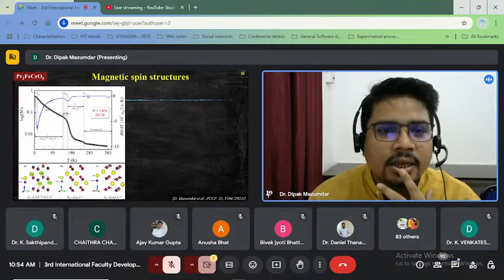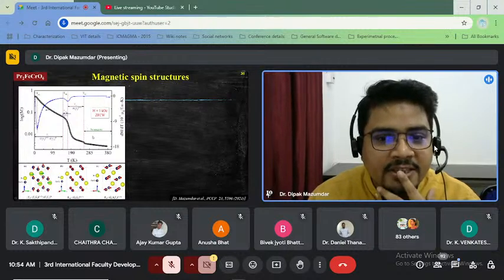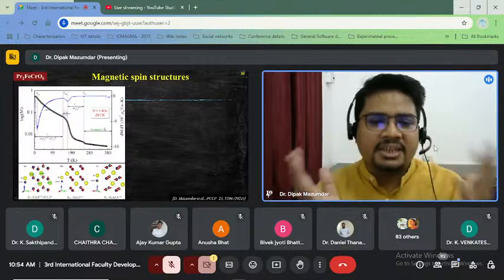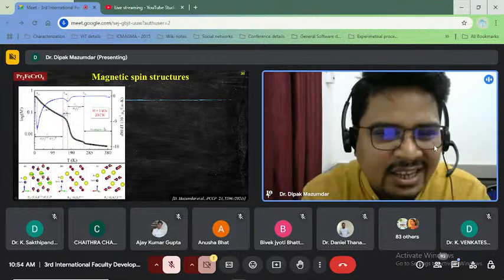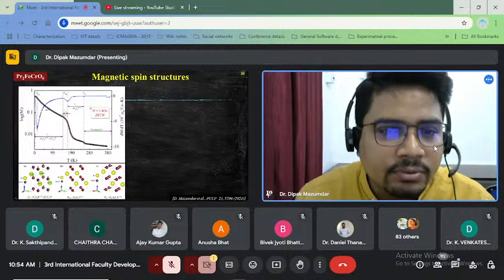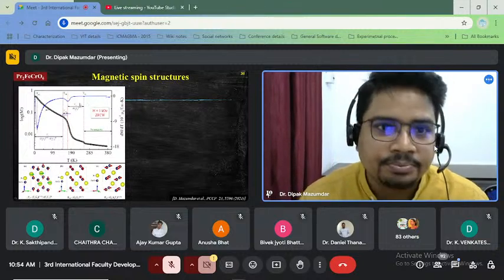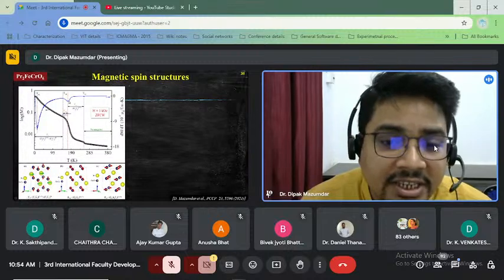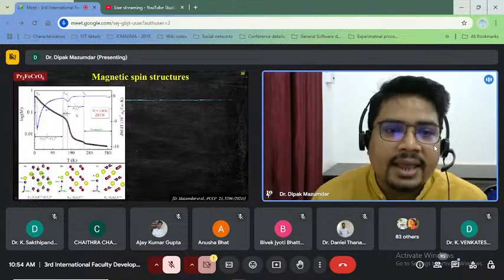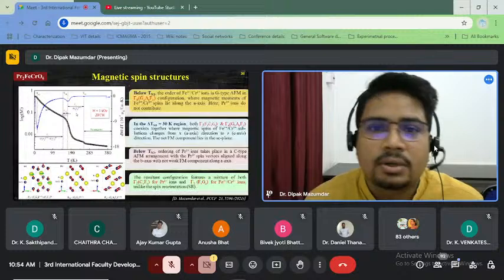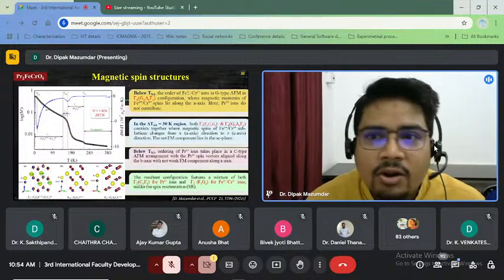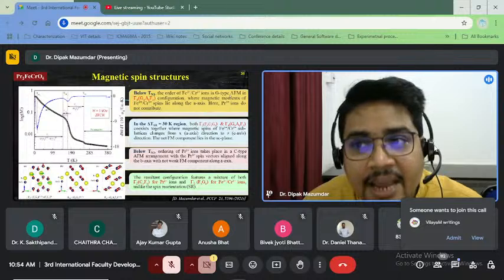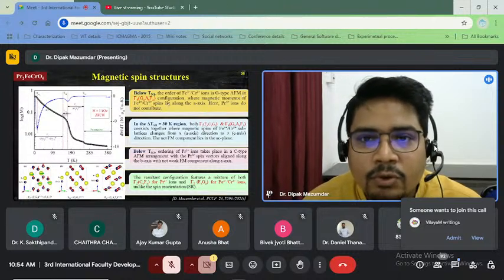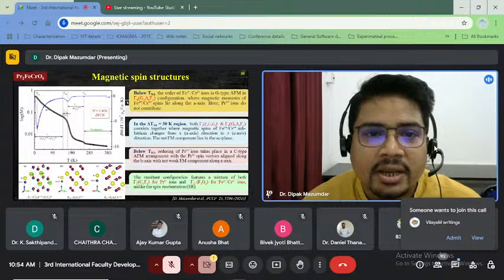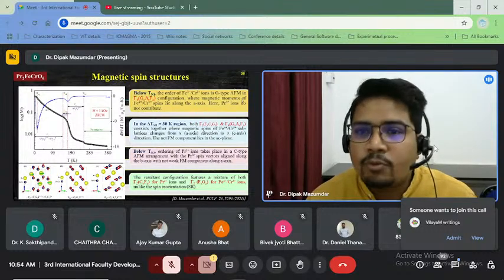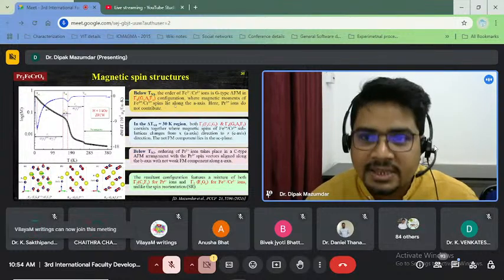So in this region, above this temperature, the system behaves paramagnetic. So here all the magnetic spins will be randomly oriented, so I did not draw any structure. I have drawn in this region from TN1 to TSR, where the spin reorientation will start. So here the system exhibits, below TN1, the order of iron and chromium ions in G-type antiferromagnetic in the gamma 4 configuration. So G-type antiferromagnetic order will take place here, while the magnetic moments of iron and chromium spins lie along the A-axis.